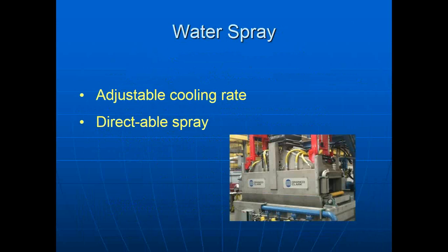The next step then is water spray. These would be larger nozzles, and this would look more like a traditional spray that you would think of, hundreds of gallons per minute. With the spray nozzles, you have the ability to adjust cooling rate. You can adjust the flow, adjust the volume, select which nozzles are on and off, which gives you ability to direct the spray and have some controllability.